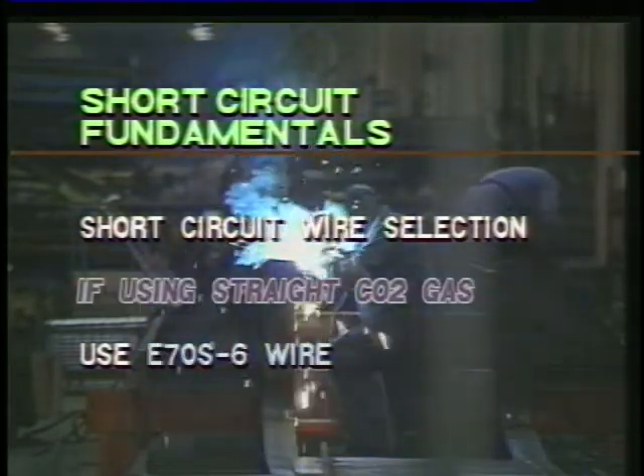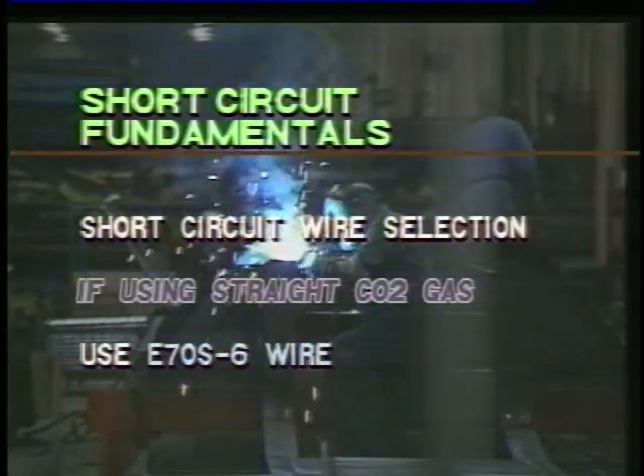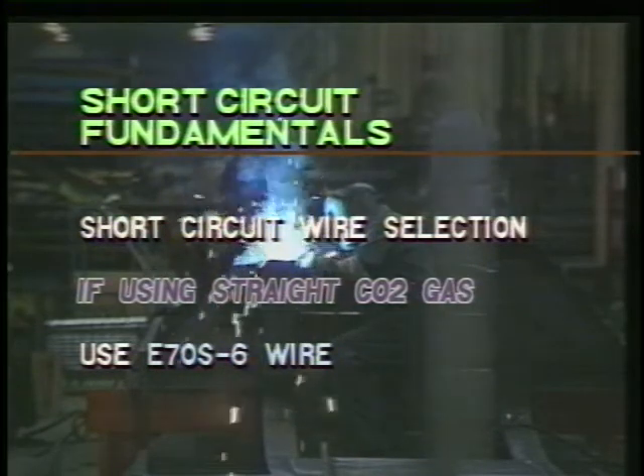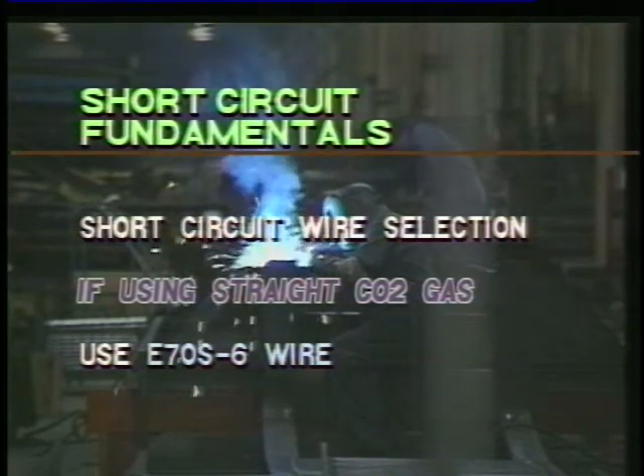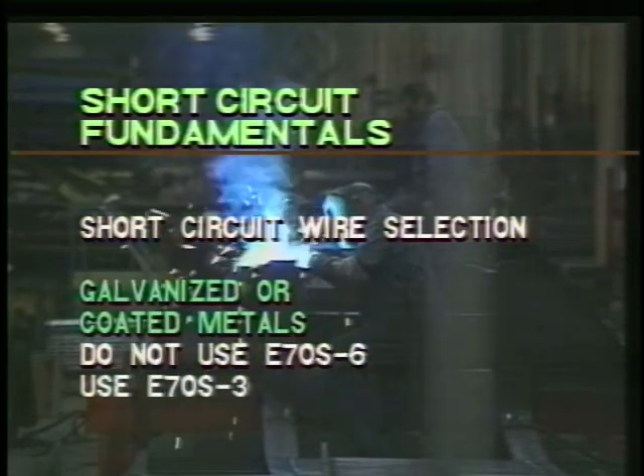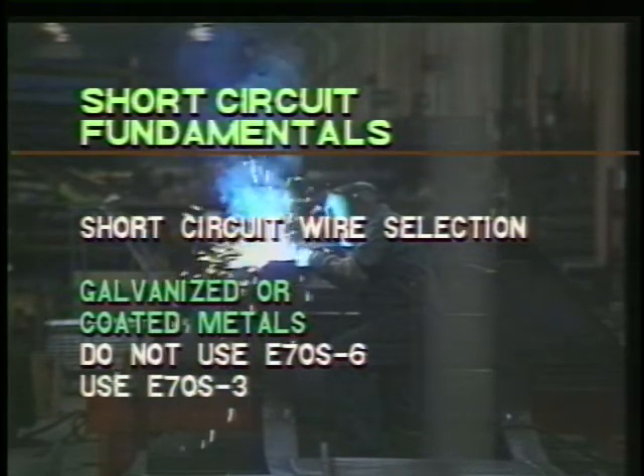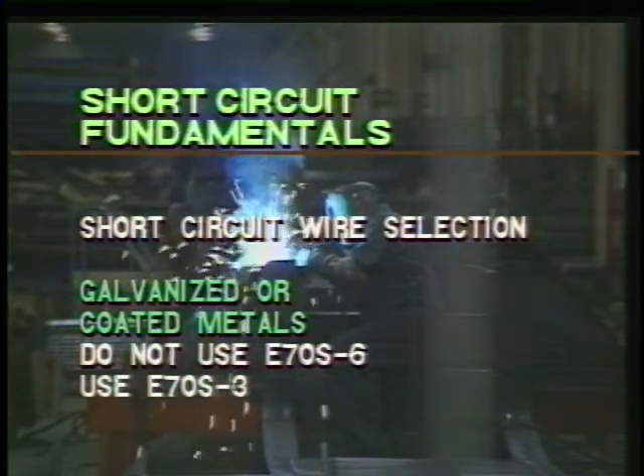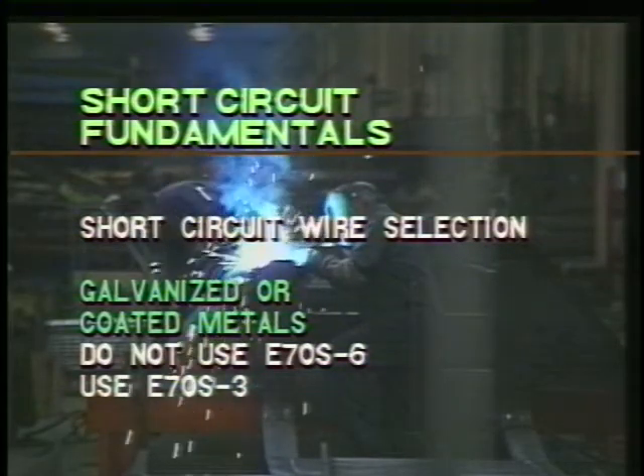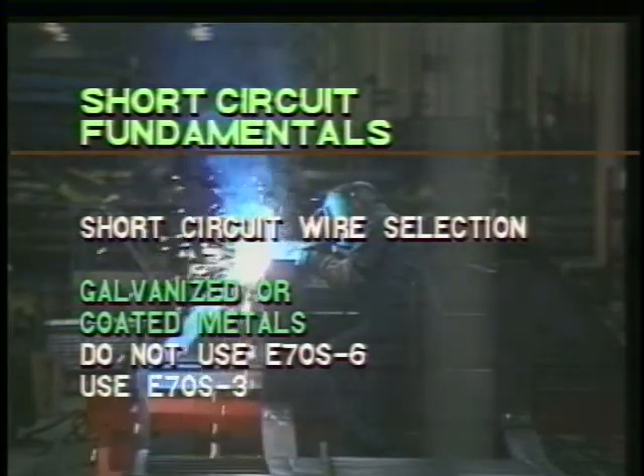If using straight CO2 gas, use a high silicon wire, such as an E70S-6. When welding coated or galvanized steels, avoid the E70S-6 wires. High silicon wires promote cracking. Use E70S-3.